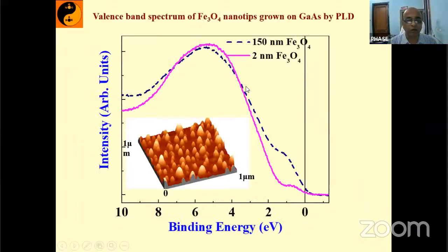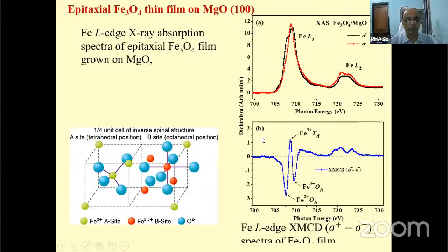I already told you about this sample when I told you about the photoemission beamline. This is the 2 nanometer Fe3O4, and this is the 150 nm thick Fe3O4. So what is the difference? Here we have seen only the electronic structure difference, that the density of states is slightly different in this sample. But Fe3O4 is a very important magnetic material, used in recording media and other things. So what is the difference between the magnetic properties of 2 nanometer and 150 nanometer? Here we have done the XMCD measurement of both samples.